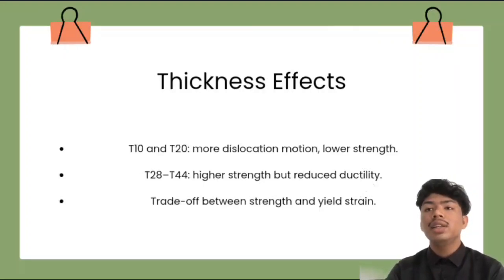On the other hand, T28, T36 and T44 show the highest flow stress, meaning the strongest materials. However, this also appears to reduce plastic deformation, indicating a trade-off. The T28 model gives the best balance. It achieves the highest flow stress with a manageable amount of ductility. This highlights that interface thickness is a key design factor. Thinner layers improve ductility but reduce strength, while thicker layers increase strength but limit deformation. Designers must choose the right thickness based on whether strength or flexibility is more important.